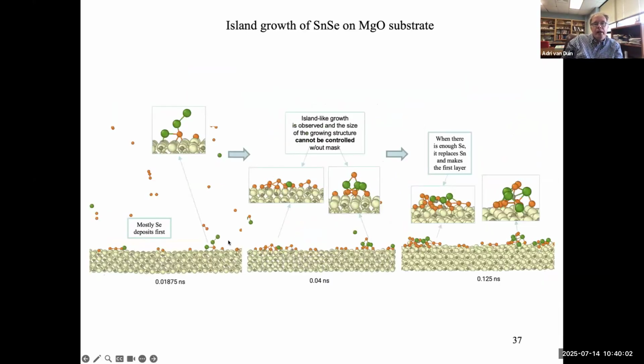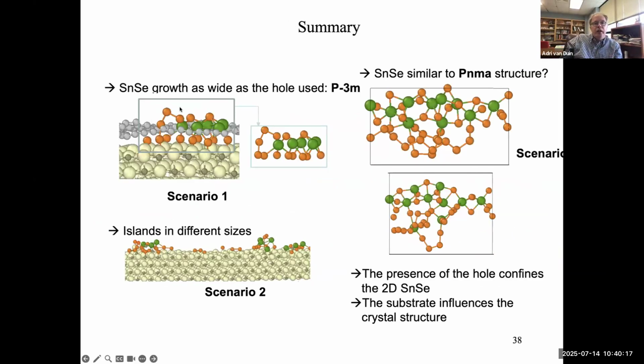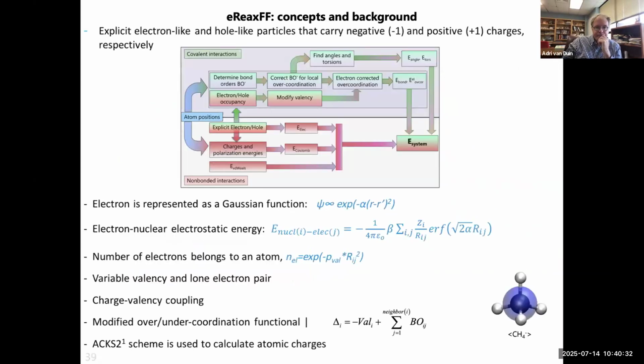If we just grow on the magnesium oxide, we do see some template effect, but we don't seem to be able to control stoichiometry very much. And we get all sorts of different cluster sizes at different times. So the graphite mask is very important in controlling our size. Only when we use both a graphite mask and magnesium oxide do we get a very nice crystalline growth. In all other cases, we don't control growth size and we don't control crystal structure terribly well.